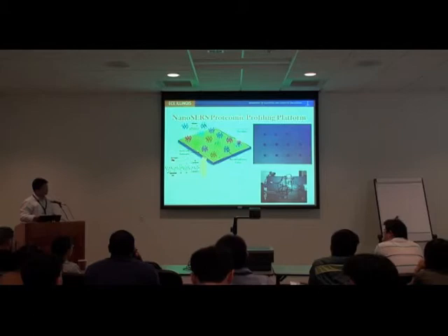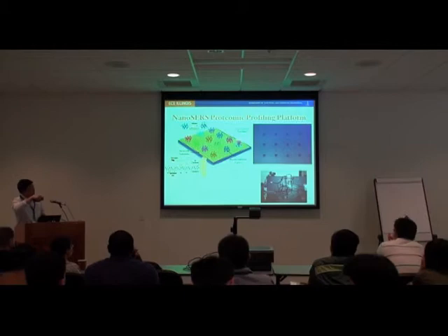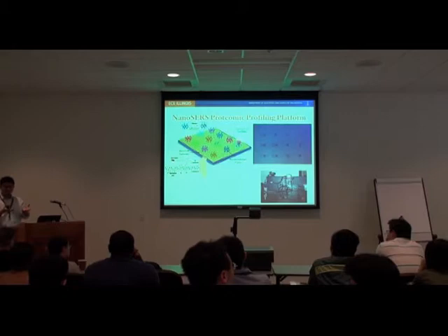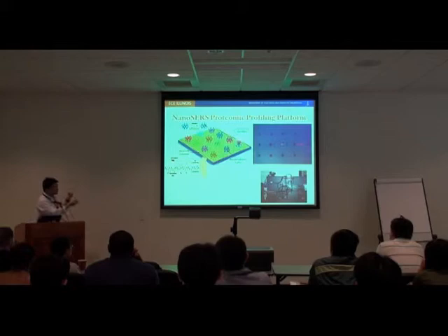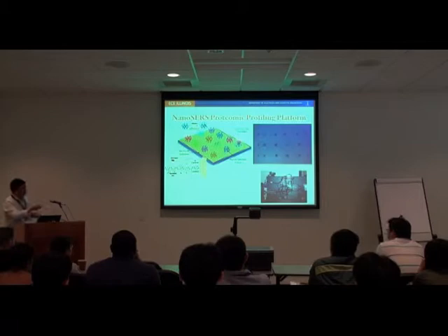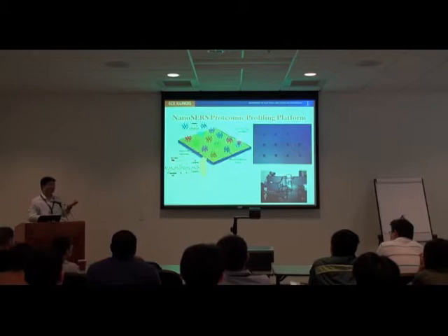So if we scan a laser over it, you'll find whenever the laser gets on top of these nanostructures, the intensity has been increased many, many times. That's why you can see those bright spots when the laser is shining on those dark squares. When the laser is shining on the smooth metal surface, you don't see a lot because you don't have a very high electromagnetic field enhancement.